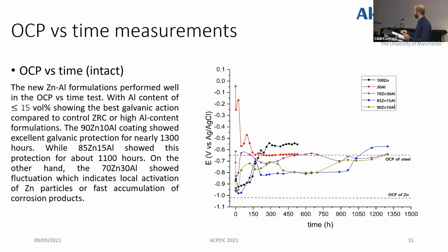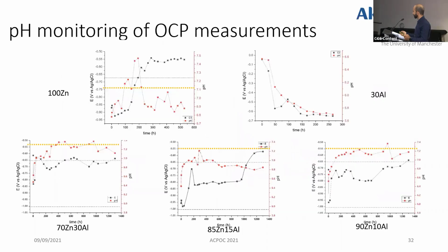So the longer the time below the OCP of the steel, that means more galvanic action offered by these coatings. So the coatings with 10 to 15 percent aluminum content offer more galvanic action. But for the higher one, which is 70 zinc 30 aluminum, with higher aluminum content, it shows some fluctuation, and this is maybe because of local activation of zinc or accumulation of zinc corrosion products.